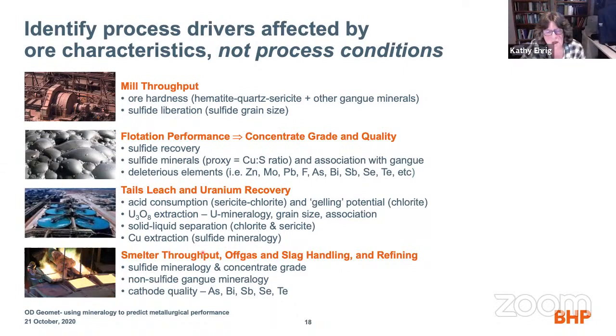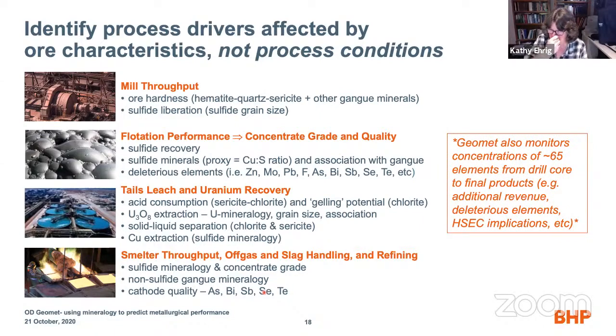Things that impact the smelting and refinery side of our process are the sulfide mineralogy, the concentrate grade, which is a function of that sulfide mineralogy, the little bit of gangue minerals in there, and things like arsenic, bismuth, selenium, tellurium, and antimony, which are part of the cathode quality suite of elements. For geomet, we not only worry about those, but we monitor most of the periodic table, because we're also looking for potential additional revenue streams, anything that's deleterious to our entire circuit, anything that might have HSEC implications, and things that might impact our final tailings storage system.